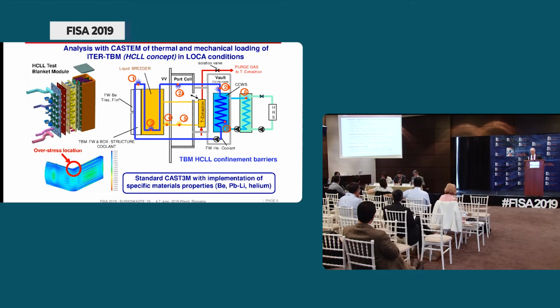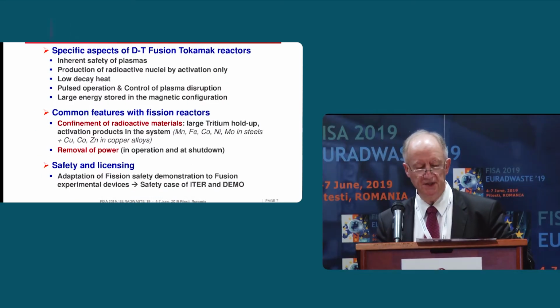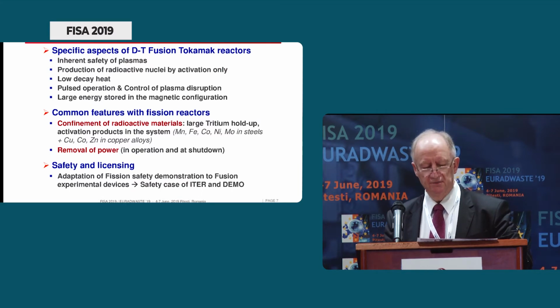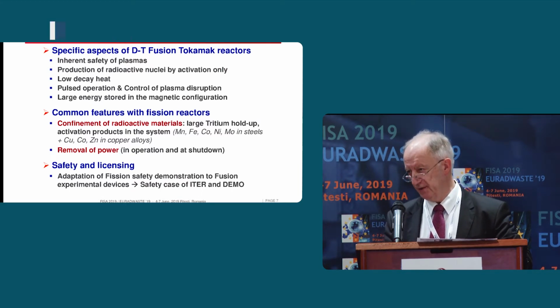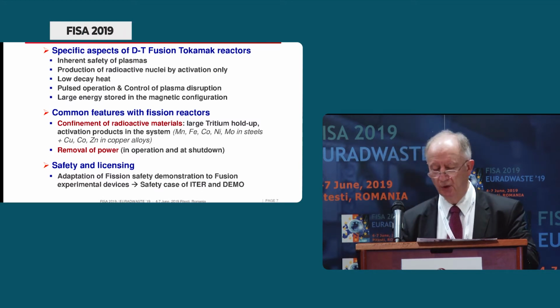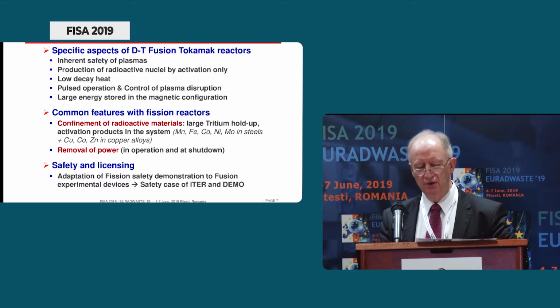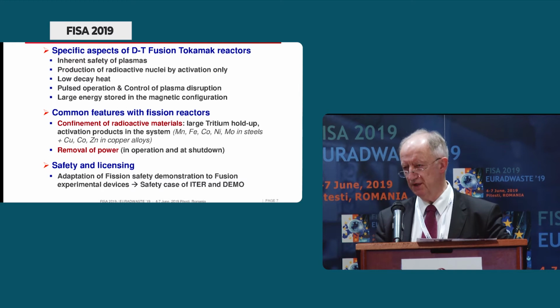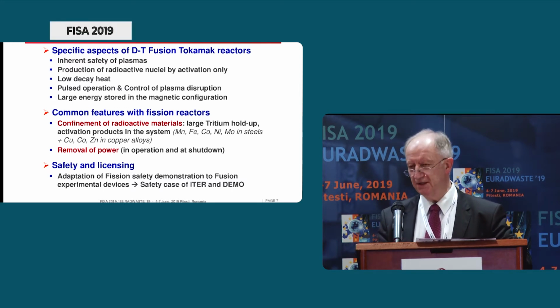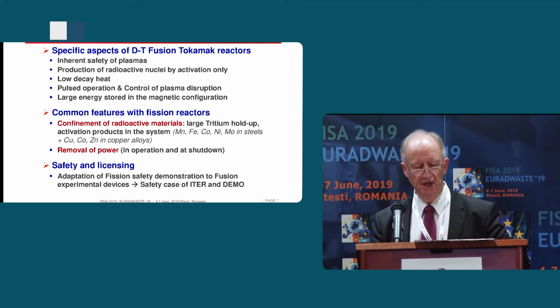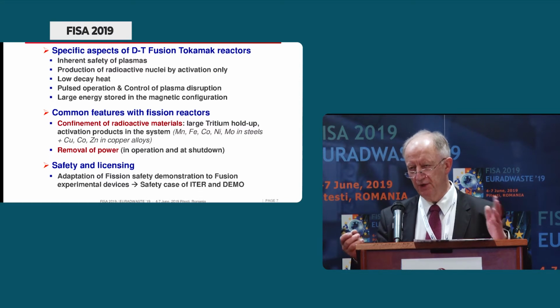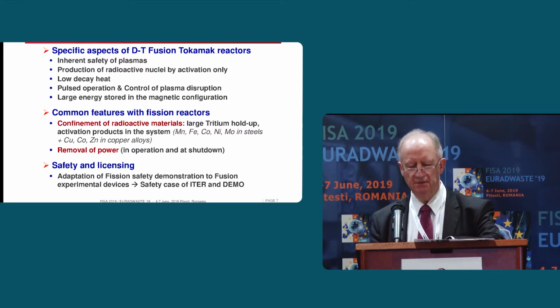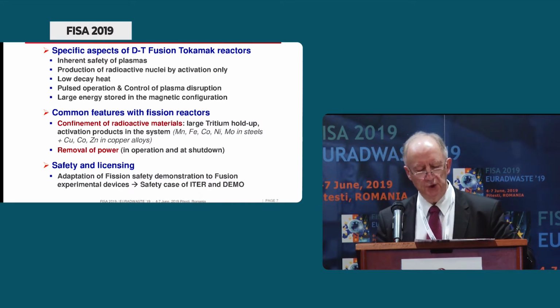So in brief, regarding safety, there is an inherent safety of plasma, so nothing like a reactivity type of accident. However, cooling accidents may occur, as there is heat generation within the blanket and the first wall, including decay heat, even though the orders of magnitude are far less than the decay heat from fission products. But activation products still generate heat, and active removal of this decay heat should occur. And also, you have understood that appropriate confinement with the three barriers, as required by the defense in depth safety approach, applies to tokamaks with ignited plasma in a more complex geometry.